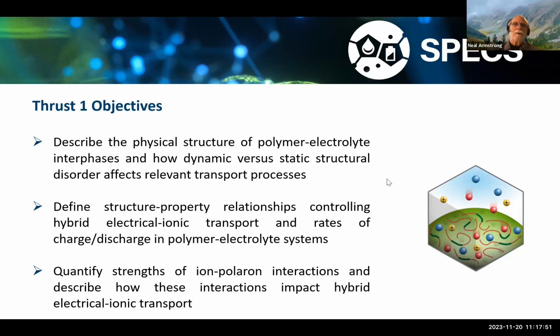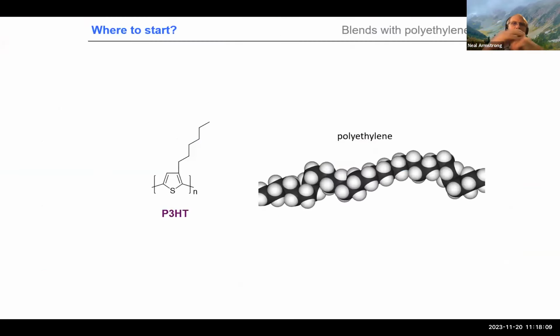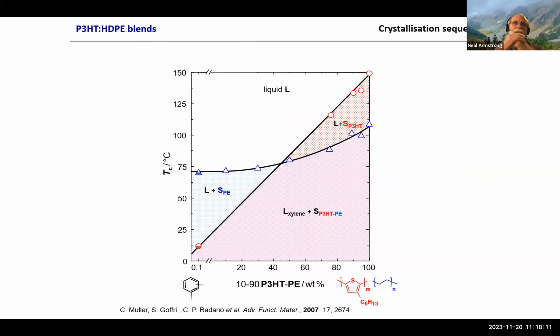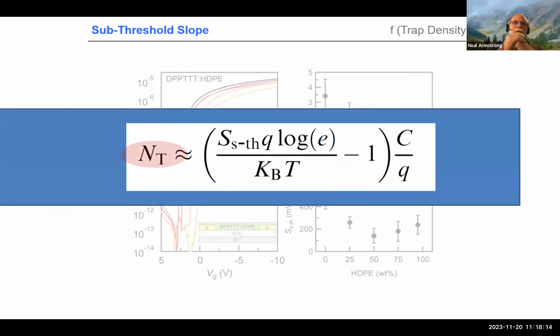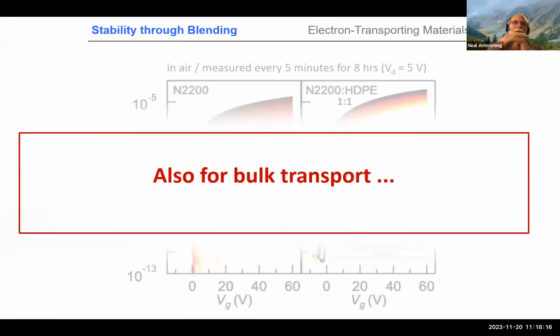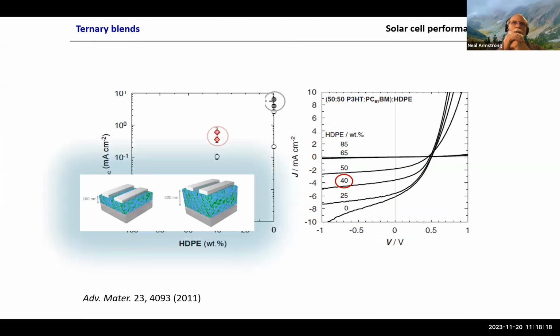So I had a question. When you first did the blending with an OPV donor acceptor blend, I was intrigued by those results because when you account for dilution, it looked like you were getting the same net photocurrent. So that tells me that the donor acceptor blend is essentially retained in its properties, even though you've added this host polymer to mechanically strengthen that. Is that right? And it is actually, yes, because we did the phase diagrams.